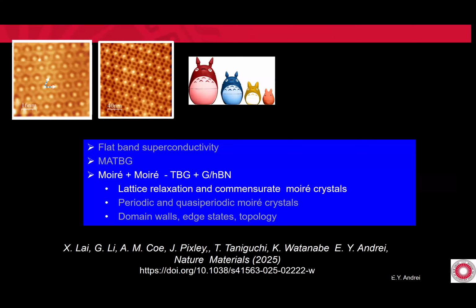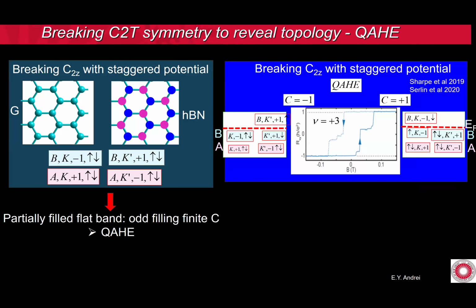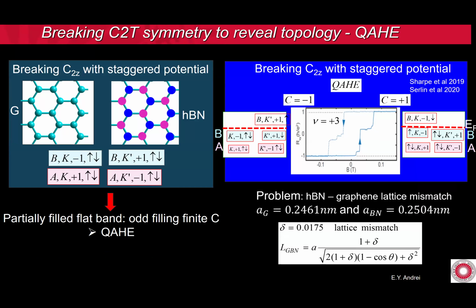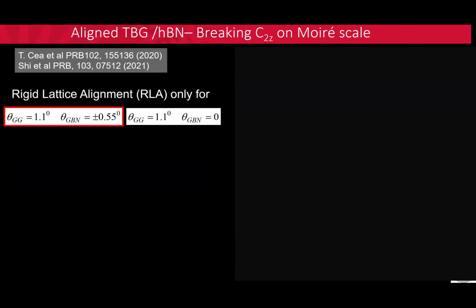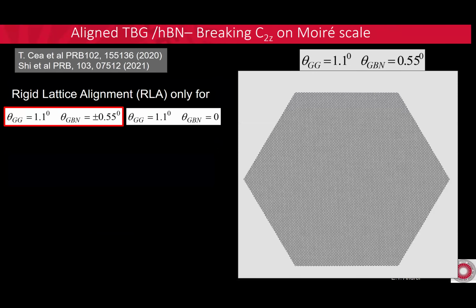Okay, next topic is Moire. Back to your question, Paul. This is a wonderful story, but graphene and boron nitride don't have the same lattice constant. It's off by a couple of percent. So you can never really perfectly align it except at 2 points. If you want to be at magic angle, the twist angle between the bottom layer and the graphene has to be 0.55, or 0, and that's it.